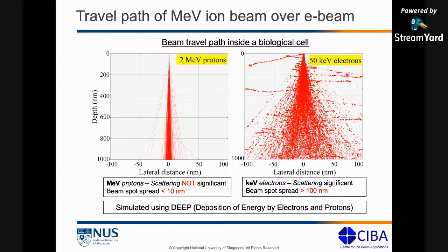Electrons being much lighter than protons at a lower energy, the moment they enter the cell, they start to scatter around, right? And by the time you go down to the order of more than 100 nanometers, compare this to protons. Now you have 2 MeV protons. Protons are much heavier than electrons. At higher energies, what you get is a streamlined entry into your cell. In fact, if you look at 200 nanometers or 400 nanometers, the scattering is practically insignificant. When you go down to 1 micron depth, you will have some amount of scattering. It's about 10 nanometers or less, but much better than what we see in electrons. So you have this streamlined entry effect into your material with protons.